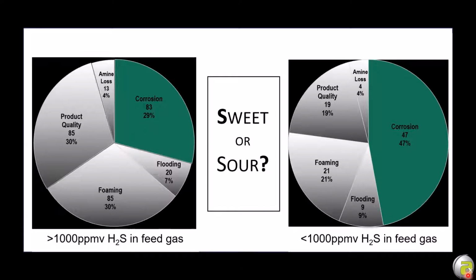limit. So on the left side, it's even with sour gas, corrosion, meeting spec, and foaming are still the big 3. And on the right-hand side, as we process more and more CO2 and less H2S, you can see that corrosion now becomes a much larger piece of the pie. 47%. So almost half of the system failures in low H2S facilities are related to CO2. The simple question that some of you might be asking is, well, why is that the case? What's the difference with high H2S versus low?